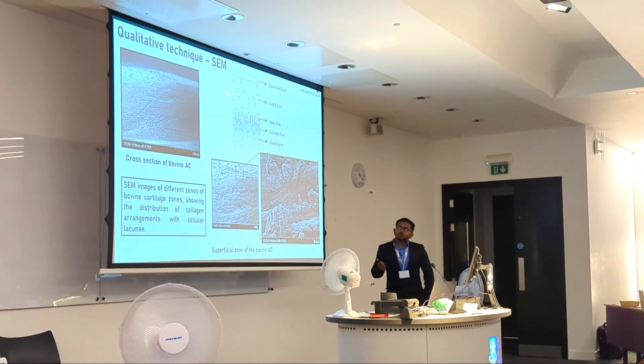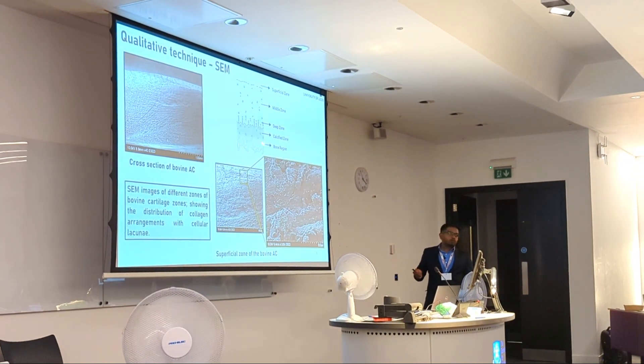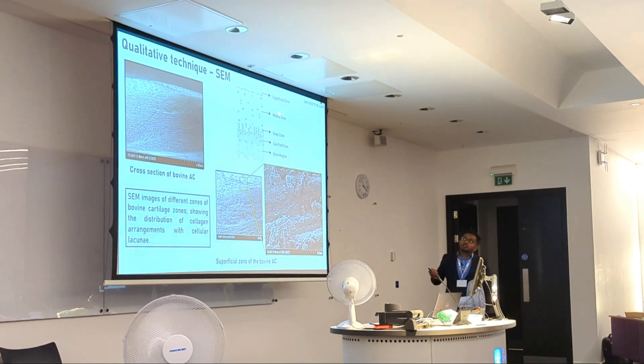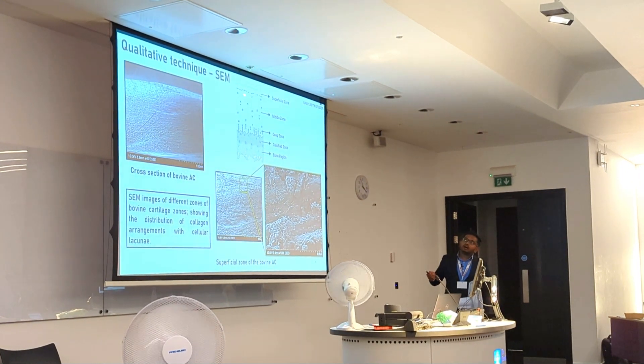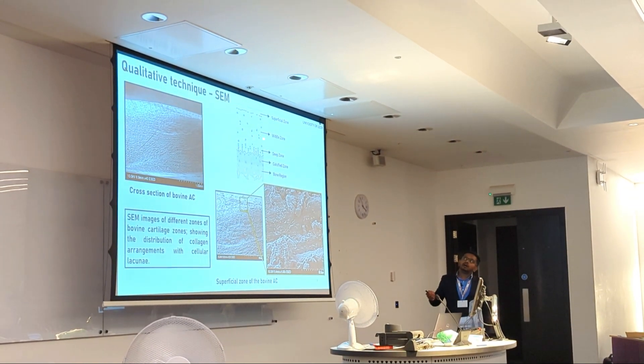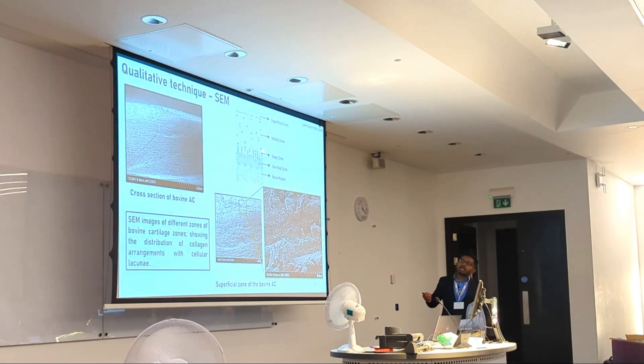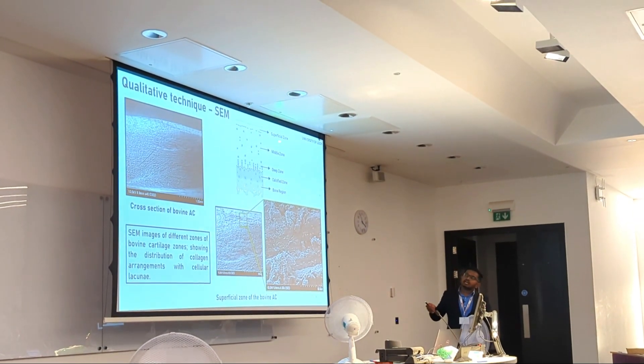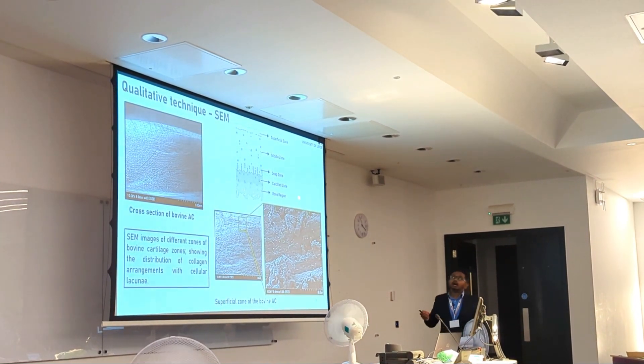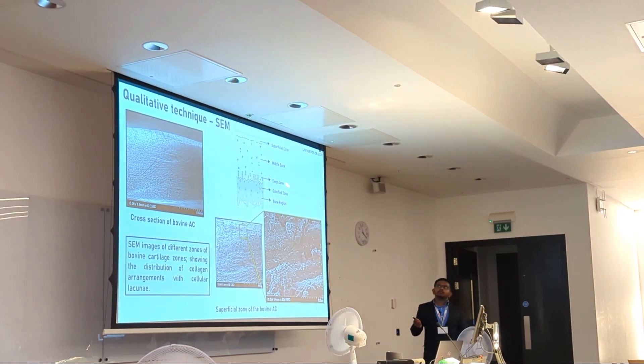Qualitative analysis is performed through SEM imaging. In cartilage, there are different zones each with different arrangements of collagen fibers and proteoglycan fibers. The superficial zone has a parallel arrangement of collagen fibers; the middle zone has roughly a 45-degree arrangement in bovine cartilage and a random arrangement in human cartilage; and the deep zone has a radial arrangement. These three zones — superficial, middle, and deep — explain how cartilage degeneration takes place.